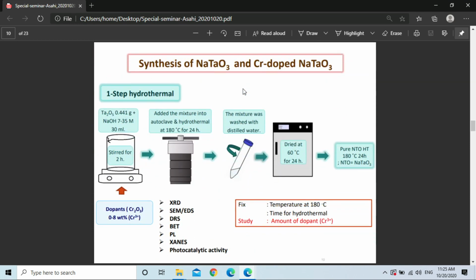Let me show this simple synthesis process. We start with a tantalum oxide and sodium hydroxide mixture, and then we get the suspension and transfer it to an autoclave at 180 °C for 24 hours. Then we separate the powder, wash and dry, and get the sodium tantalate sample and do the characterization. For the doping material, we use chromium oxide as the dopant and vary the amount of chromium dopant from 0 to 8%, by mixing it in at the beginning of the suspension.